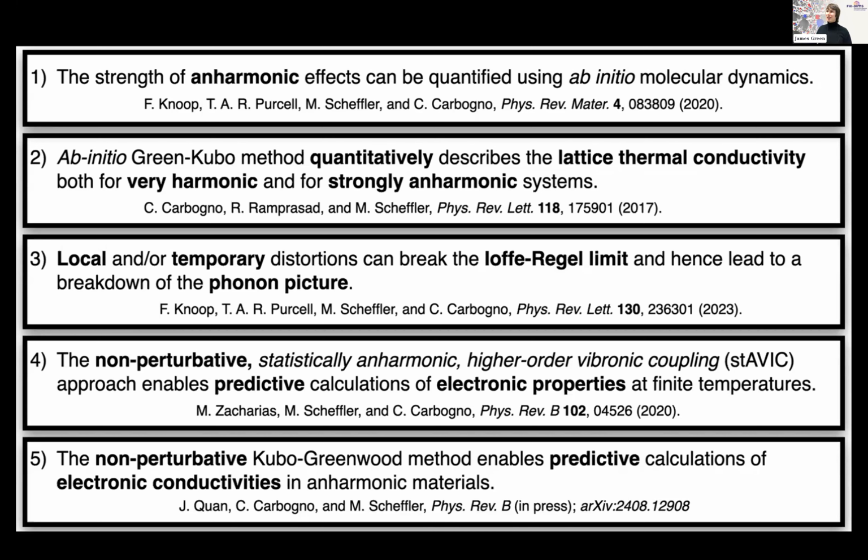Okay, next question to Christian, then from Rocco. So are the Green-Kubo or Kubo-Greenwood approaches feasible to capture also the defect-induced contribution to resistivity, either thermal or electric? In principle, this is not a problem at all. Formally, it's no problem. It involves more calculations. If we want to model a defect, we have to use the respective supercell, make sure that the defect and the defect concentration is well modeled in that supercell, and then it would capture these effects naturally without any further theoretical ado, correction terms, and so on. So this would be naturally captured.